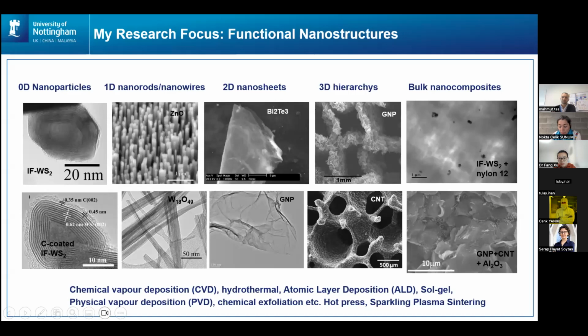Normally we use chemical exfoliation to prepare graphene layers. Hot press and spark plasma sintering are the two technologies we use to prepare our ceramic composites and metal composites. My PhD was focused on inorganic fullerene tungsten disulfide, because it's a super shock absorber and super solid lubricant.